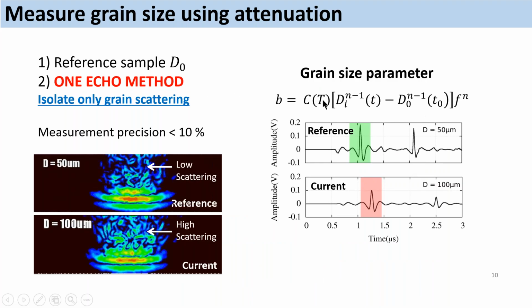About 10 to 15 years ago now, maybe even 20 years ago, a new method was applied by the Canadian CNRC, where the method is to use one single echo, which has therefore propagated the same propagation distance, and which isolates the contribution from grain scattering. So what we have to do is measure a waveform in a reference sample, and while we measure the current waveform by doing the ratio of those 2 echoes, we will have only the contribution from the grain scattering in the attenuation. We can then write the attenuation as a function of the frequency and the grain size as such, to build some calibration and determine grain size from this measurement of the attenuation.